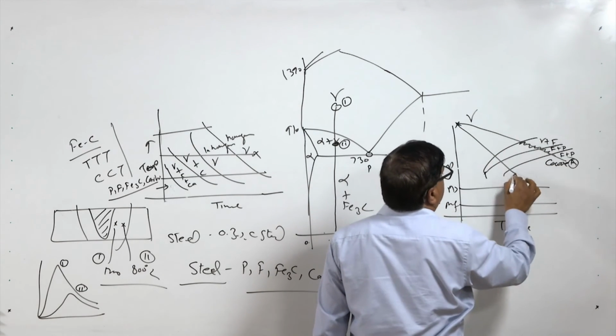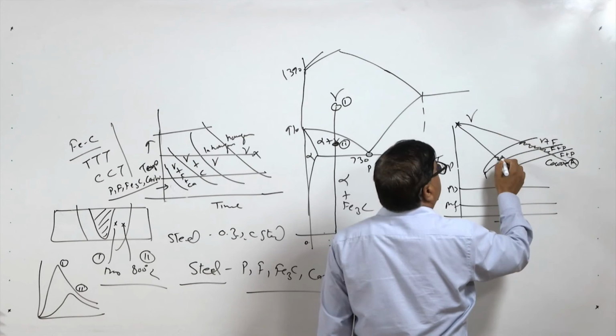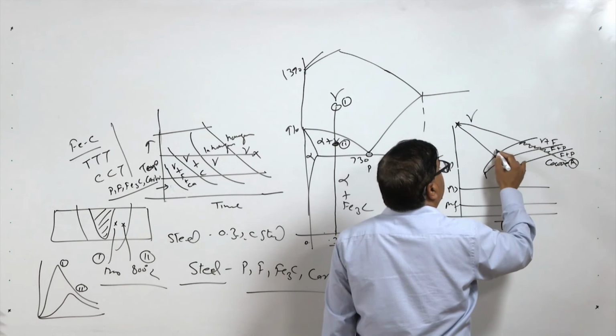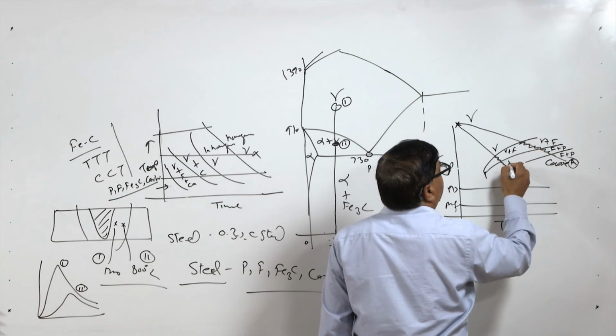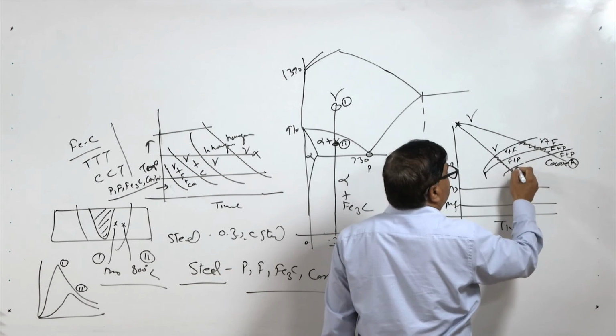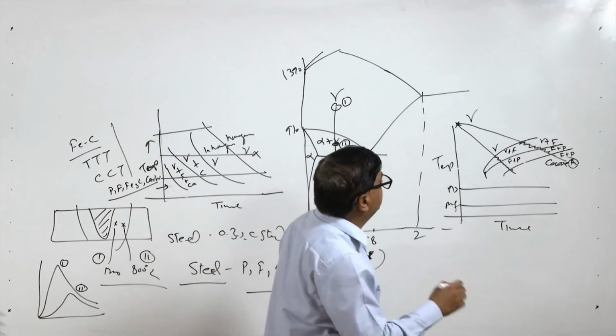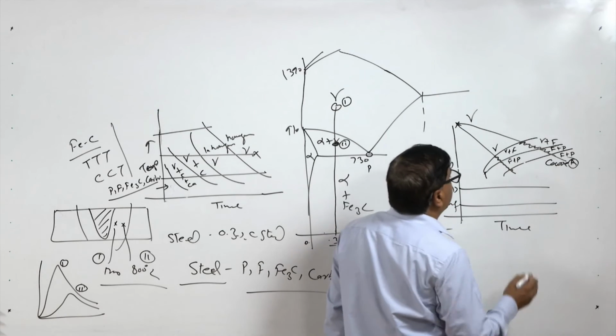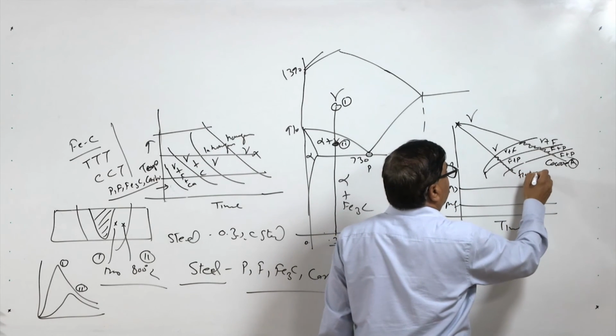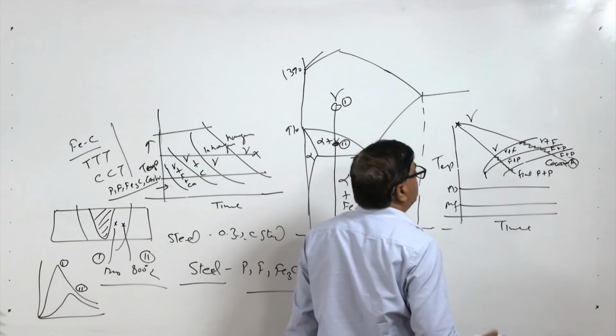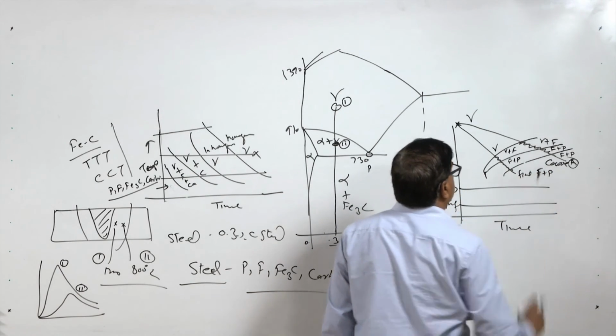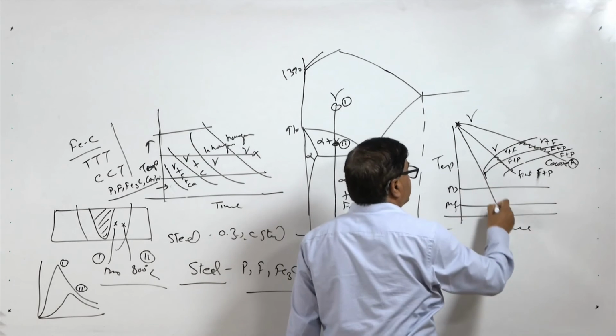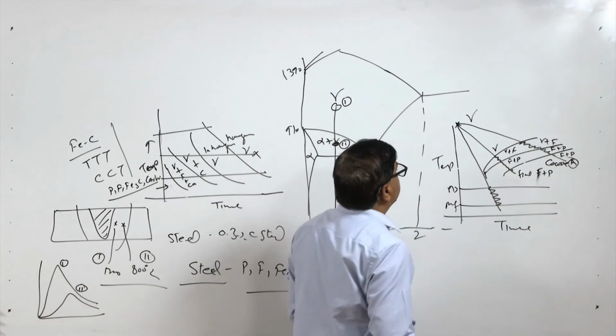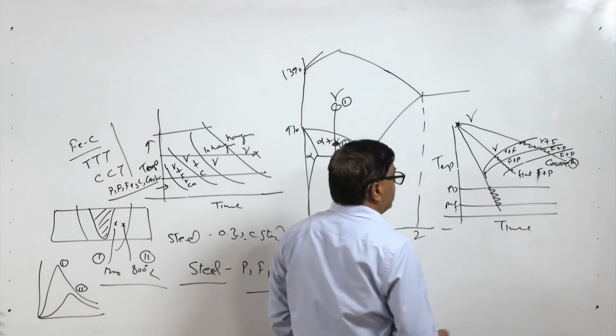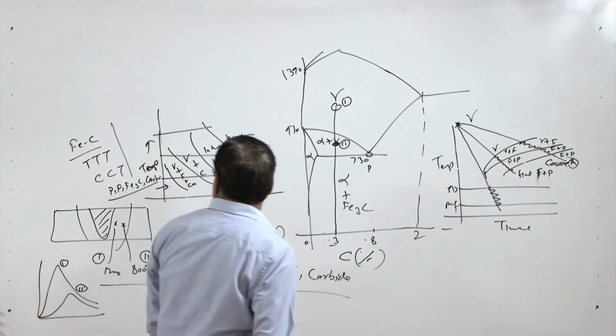If we use a higher cooling rate like this, here also austenite plus ferrite, here ferrite plus pearlite, and then here the transformation of austenite into pearlite will complete, and we will have fine ferrite plus pearlite in this area. If the cooling rate is really fast, then we will have a whole transformation of all austenite into martensite, and we will get the complete martensitic transformation.